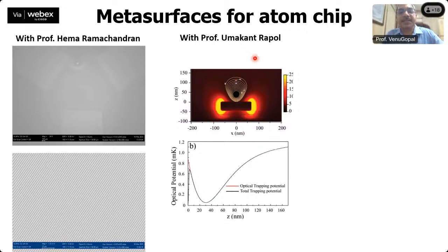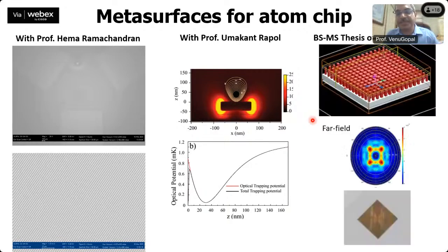But this was with Professor Umakant Rapol, where we showed that if you take a metal disk, either gold or silver, and we showed that gold is better, the top of the disk acts like a trap potential. We calculated that, then did near field measurements to show that we do have this trap-like potential, and it's suitable for trapping atoms on top of these disks. The actual trap measurements were never done, but I've seen in literature later on that polystyrene beads have been trapped on top of such structures.